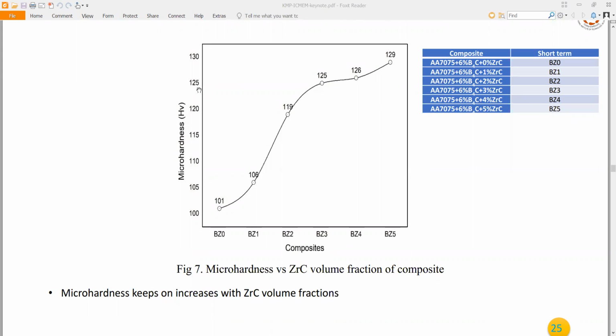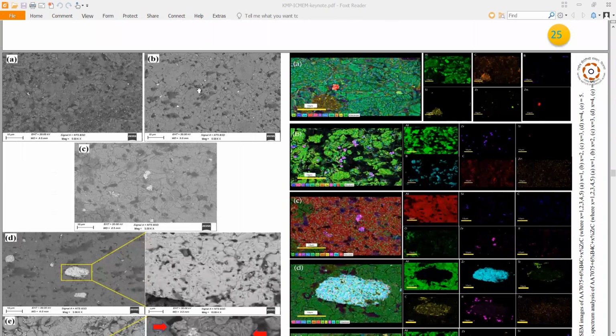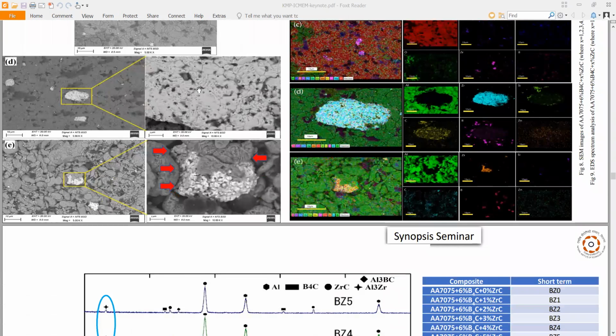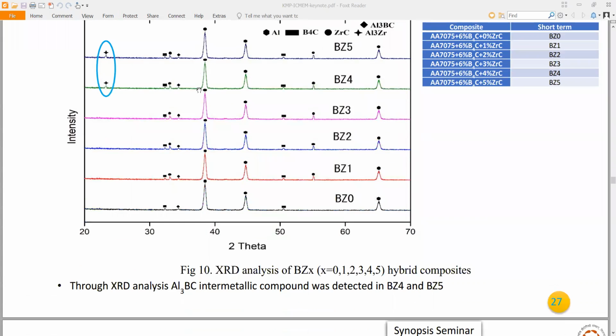So what is the conclusion? We have arrived that micro hardness keeps on increasing with ZrC volume fraction. Then we can see figure 10, the XRD analysis of BZx, where x is equal to 0, 1, 2, 3, 4, 5 percent, for the hybrid composites. In the XRD analysis, Al3BC intermetallic compound was detected in BZ4 and BZ5.